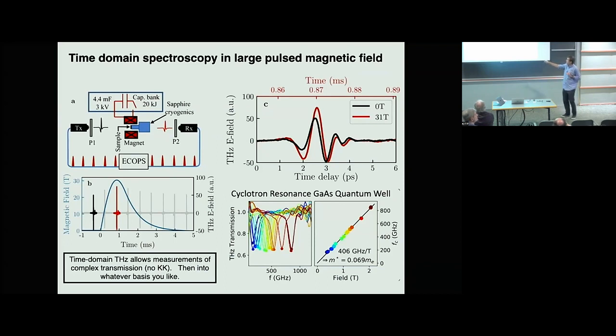We can do these experiments now where in a single pulse we get enough information to measure a spectrum. In a single pulse of a magnet here, the field goes up to 30 tesla and then ramps down over the course of milliseconds, and we can get boom, boom, boom, 5 or 6 samplings of different magnetic fields, measured all the way out to 30 tesla. This is the transmission as a function of frequency on a gallium arsenide quantum well, and this is just the plot of this minimum at different fields lying on this straight line, and from eB over m, you can infer the m, and that's the accepted mass of this 2D electron gas in gallium arsenide here.